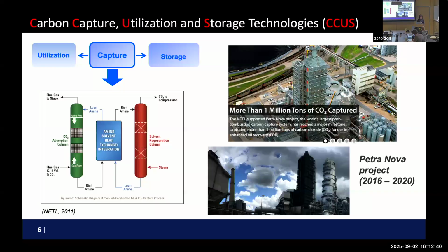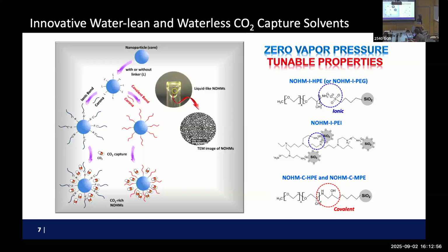But if we can try to think about innovative materials to capture CO2, the second generation of liquid CO2 capture solvent was water-lean, waterless. Just get rid of all that water and let's keep as much amine as possible. So the materials I worked on at Columbia were something called NOHMs. NOHMs are nanoparticle organic hybrid materials. In fact, the first generation of this material was developed by Lynden Archer, the polymer guy at Cornell. Very nice guy I worked with.